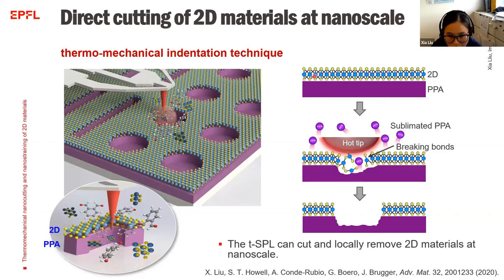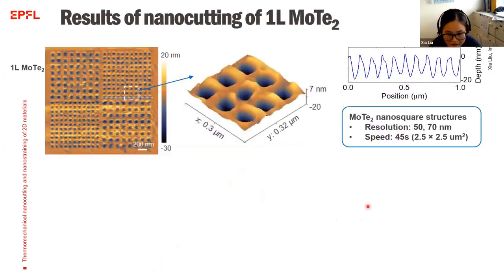You can see first a 2D layer is transferred on top of the PPA with the van der Waals interaction, so there is no sliding between the 2D layer and the PPA. Then the hot tip approaches the 2D material, and of course is applied with sufficiently high force, such that the chemical bonds in the 2D layer can be broken. Meanwhile, the PPA underneath will sublimate and escape from the layer, which results in the sublimation of the polymer. In the end, a deeper indent can be created, and the 2D material is removed here. So this is the ideal case. So how do we do it?